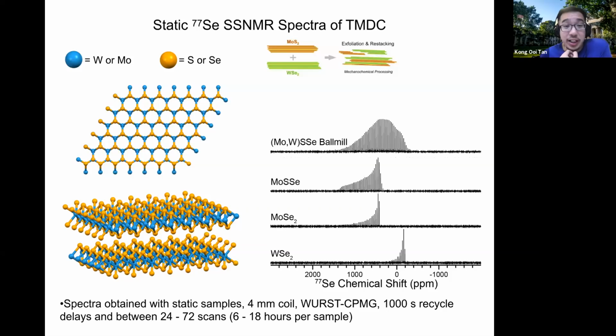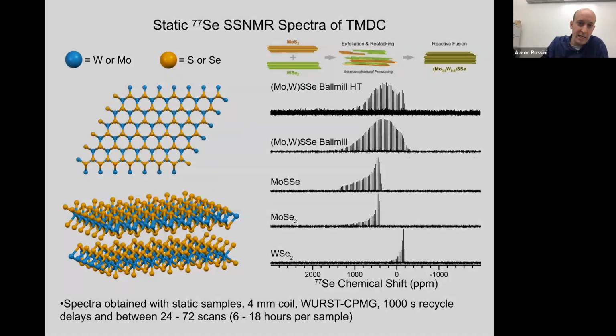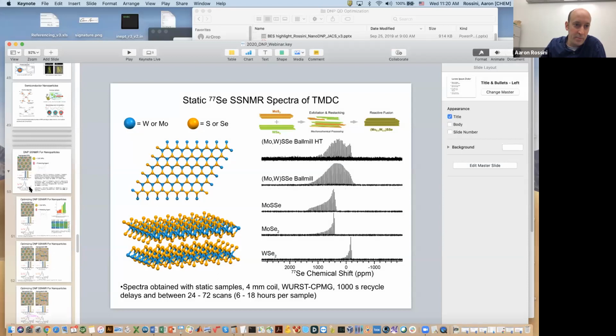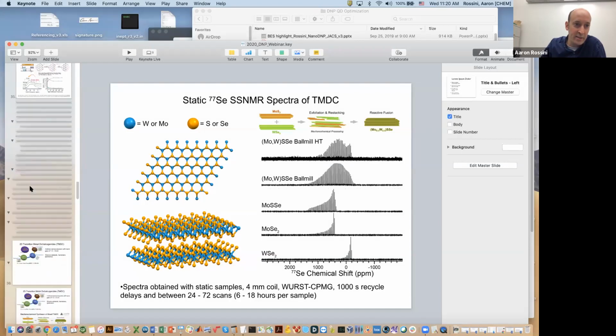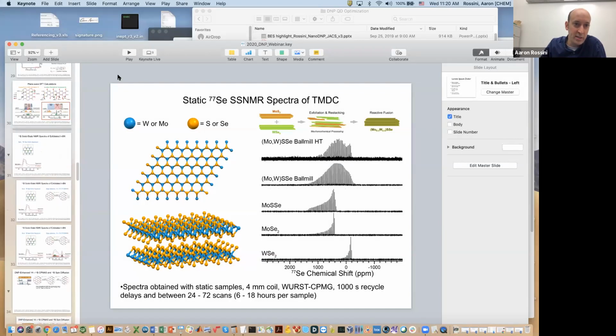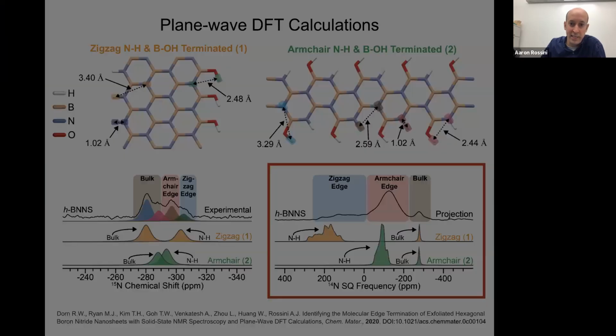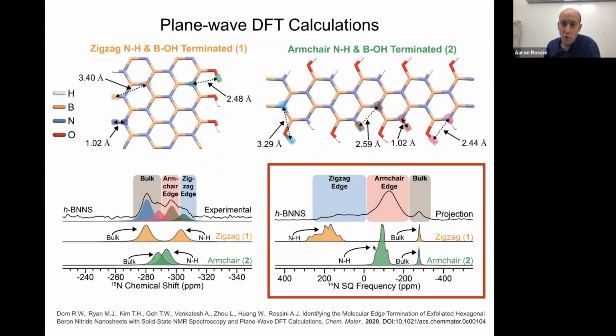The improved resolution of 14N with respect to 15N spectra is quite remarkable. Is it due to the second order isotropic quadrupole shift? Yeah, that's exactly it. When you do the N14 experiment, this is done at a 9.4 Tesla magnet, the second order quadrupole shift actually has a bigger effect on the peak position than the isotropic chemical shift. So that's what really helps to give better resolution for the nitrogen-14 in this case.